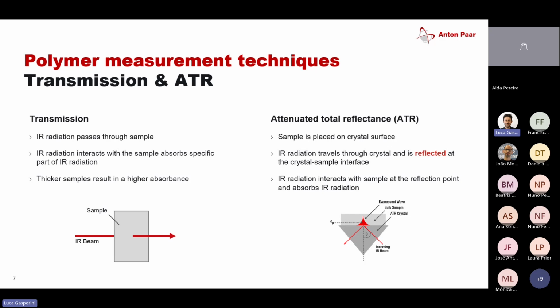So how does it work? The infrared beam hits the interface between the crystal, let's say it's diamond, and the sample, and some of this IR light will penetrate the sample. The penetration depth depends on the angle, obviously, and also the intensity of the light source, but in general it's between 1 and 5 microns. So you only measure the surface of the sample.